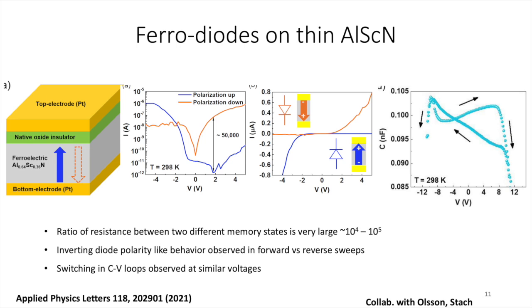It's just a sandwich structure of top and bottom metal electrodes. In this case, they are platinum. And sandwiched in between is this ferroelectric material together with a non-ferroelectric oxide material, for instance. If you look at the middle graphs over there, they are IV curves. They look like diode IV curves in log scale and linear scale. But what is important to note over here is that the polarity of the diode is flipping depending on the polarization of the ferroelectric. In other words, the ferroelectric material is flipping the polarity of the diode, making it a memristor together with a diode-like rectification function. So this is potentially useful for many things.